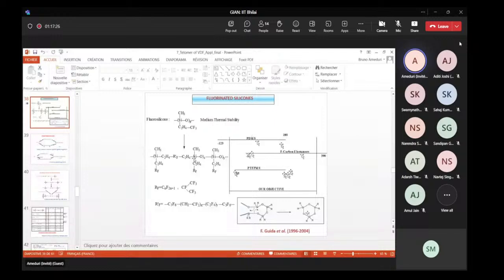Because, as I mentioned here, when you have SiO, SiO, SiO, SiO, SiO, this undergoes this backbiting to make this cycle. So if you make this silicon further, you prevent this backbiting. So the idea was also to make some side group, a fluorinated side group, either C4F9 or this gem-difluoroisopropyl. And so we decided to think about that and to prepare first.